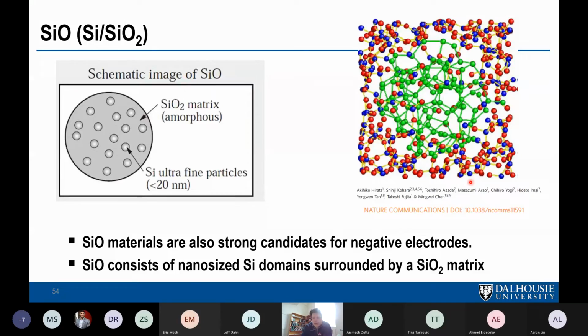And SiO, there's a lot of models of what SiO is, and I think the leading models basically state that SiO are very nano amorphous regions of pure silicon surrounded by silicon oxide, SiO2. And here in this picture, the pure silicon is in green, and the silicon that's bonded to oxygen to form SiO2 is in blue, and the oxygen is in red. Now, according to this model, because the silicon is so tiny, even though you have regions of pure amorphous silicon, the amount of silicon on the surface of these regions is roughly in the same order of magnitude as the amount of silicon in the bulk. And so that means you have a complete gradient of silicon compositions from pure silicon, which could be at the center of this pure silicon region, and as you go out, you get more silicon oxygen bonding.